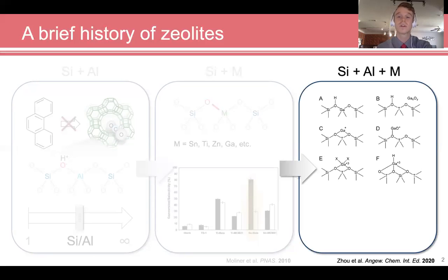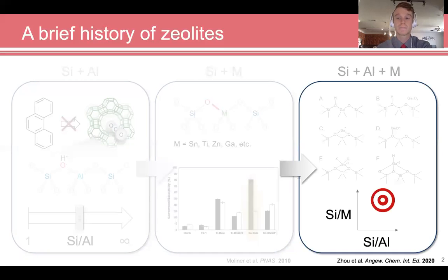So now we've also started looking into metalloaluminosilicates, which are bifunctional zeolitic materials with both Bronsted and Lewis acidity. So combined with shape selectivity, these materials offer an enormous potential, but we cannot really control their composition because we don't have a good fundamental understanding of zeolite crystallization mechanisms.